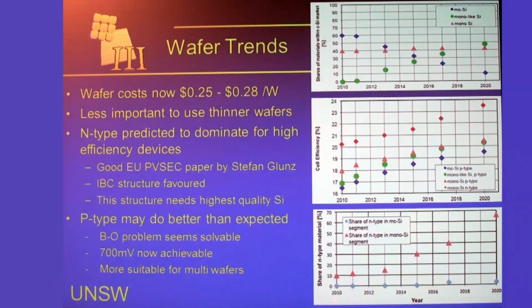And this is a graph done by that same team of experts for the International Technology Roadmap for Photovoltaics. And the blue diamonds here show the expected market share of N-type for multi wafers. In other words, they're expecting it to stay basically at 0%. The triangles, on the other hand, in red, represent the expected share of monosilicon wafers that get taken up by N-type technology. And you'll see that at the moment it's down at about 10%, but they're expecting that to increase to around about two-thirds. That there represents about 67%. So that's what they're expecting.